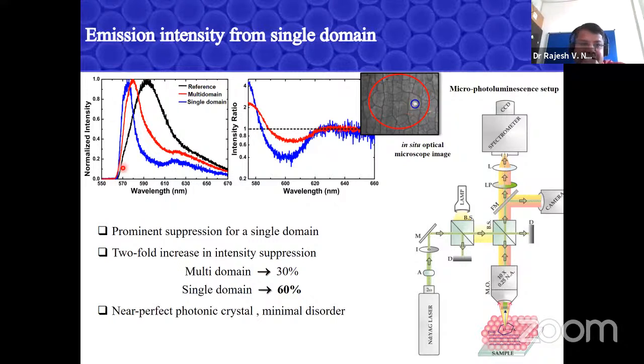We map the PL intensity as a function of wavelength. The black one is the reference sample, the typical dye emission centered around 600 nanometers. If I measure from a larger region of the sample, I get this red curve, so there's a bit of change in emission intensity. And if I measure a single domain, by which I mean this small region where there's hardly any defect, I could see a huge change in the emission intensity.